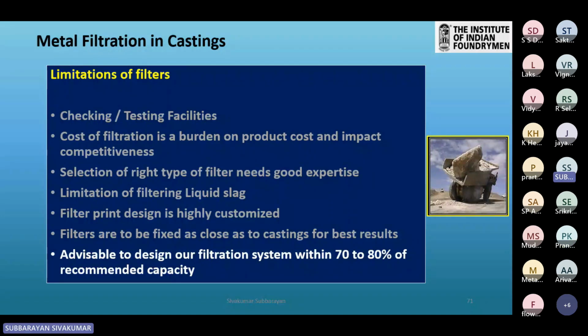One interesting input I got was from a senior foundryman from Bangalore. In one of his assignments, even after using filters, they were continuously getting non-metallic inclusions in the casting. So they listed out the probable causes and eliminated them one by one. Finally, they came to understand it was the foam filter. There is a coating used in the foam filter, and the poor quality of the coating was the root cause. It was dissolving when the hot metal went in, settling on the casting surface, and opened out after machining, and they lost a huge lot.